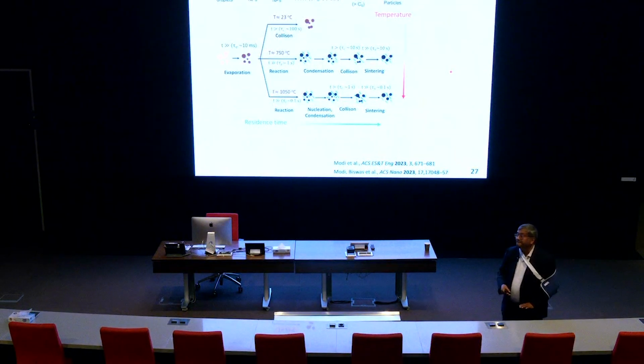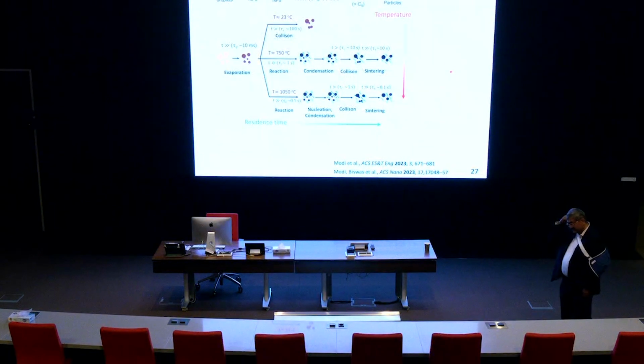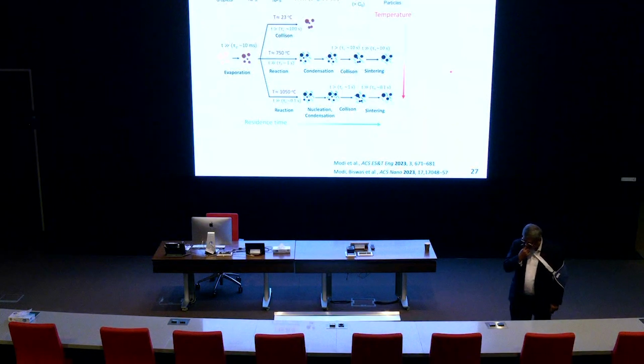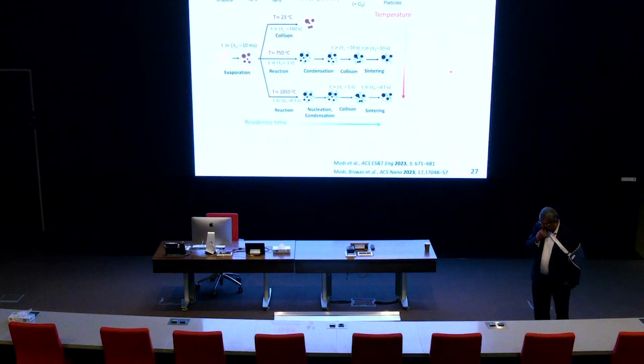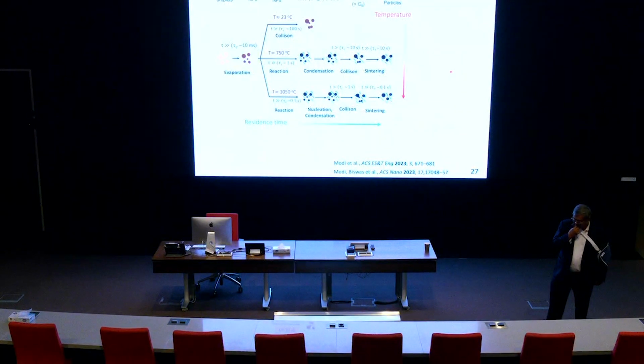Right? But if it is a particle which is created at a very high temperature, like 1050 degrees Celsius in your case, that will not sinter at 700 degrees Celsius, because it is already thermodynamically stable at that high temperature. So in your diagram, when you are talking about the sintering process, that will be strongly dependent on how the particle and at what temperature it is produced and what the constituents are. So sintering seems to be a bit of a complex scenario for me to understand, because in your slide 9, you showed that two particles can collide and can sinter. Correct. So does my temperature reach those values by such a collision? And what is the driving force for sintering?